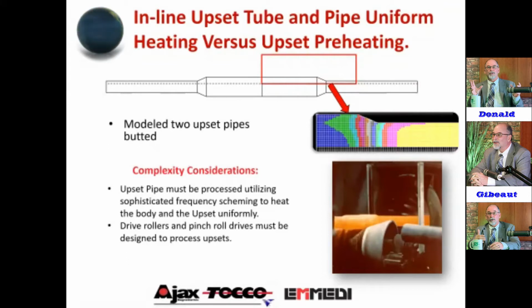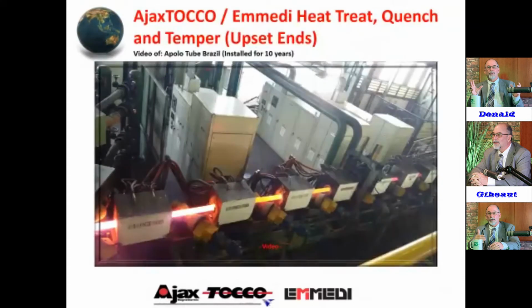And you can see that the tube of the upset is going to be closer coupled to the coil. So we precisely control that so that we can heat those upsets just about perfectly uniform to the body, and a proper delta T to get the same heat treat, quench, and temper metallurgical results. As you can see here at the lower right, I'm actually going to show you a video next of Apollo tube down in Brazil. The line's been in probably about 12, 14 years now, and they run upsets every day, and you can watch that frequency scheming work. So again, don't just take my word for it. Let me show you one, how it's working here.